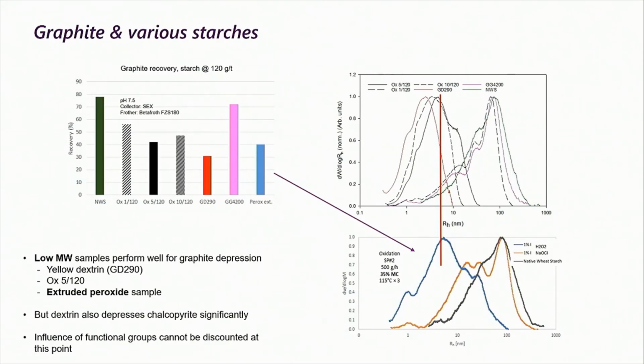The dextrin works well as well, but again, it seems to depress the chalcopyrite quite significantly as well. So there's that selectivity problem. And again, because of that change in selectivity, if we compare the dextrin with the oxidized starch, we're trying to work out the effect of the change in the functional groups, what's causing the difference between them.